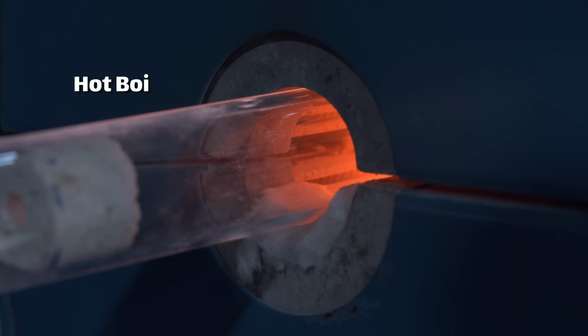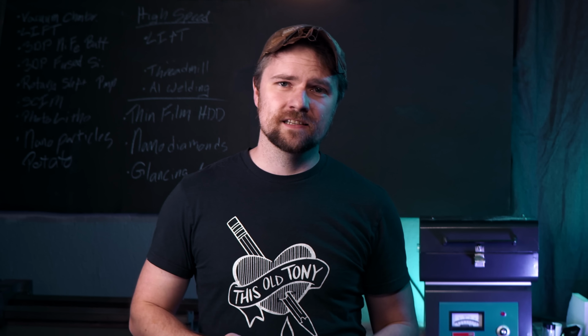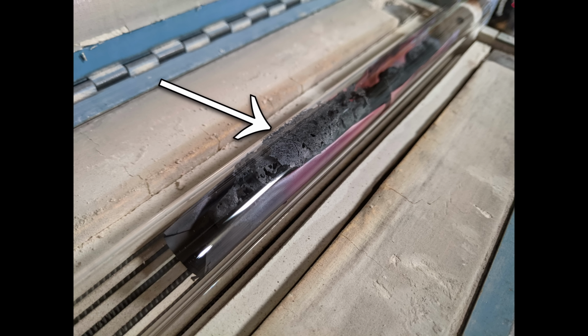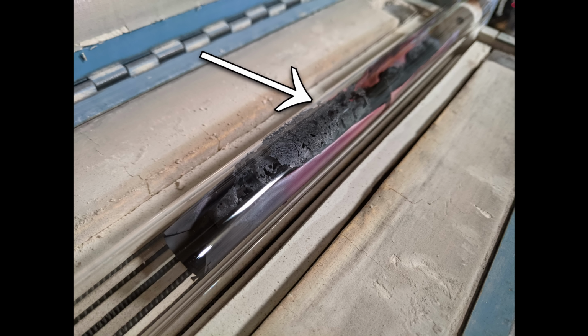From there, it's into the furnace. The paper used a ridiculously slow heating rate, 1 degree Celsius per minute. So to get up to 600 degrees Celsius, it's like 10 hours. The reason I think they did this was to slowly dehydrate the samples, because if you put the wet sample in and crank the temperature right away, all of that water is just going to boil out and you'll foam your part up and make a big mess, and it won't keep its shape anymore.